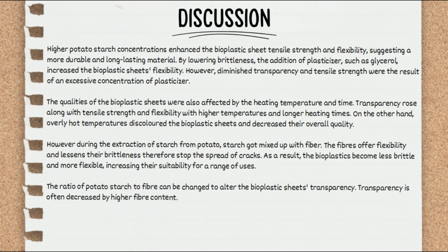Lastly, higher potato starch concentration enhanced the bioplastic sheet tensile strength and flexibility, suggesting a more durable and long-lasting material. By lowering brittleness, the addition of plasticizers such as glycerol increased the bioplastic sheet flexibility. However, diminished transparency and tensile strength were the result of an excessive concentration of plasticizer.